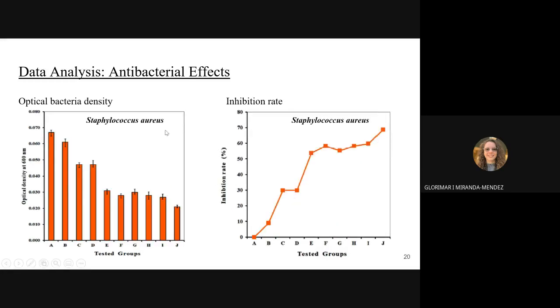And they also tested the S. aureus for their antibacterial effect. Using the same method, they obtained their optical density to determine the inhibition rate, which they determined to have a relatively more stable working high with the inhibition rate. So once they move up with the pulses, they obtain better inhibition, and reach a max of 66% inhibition with the max doped nanoparticles.